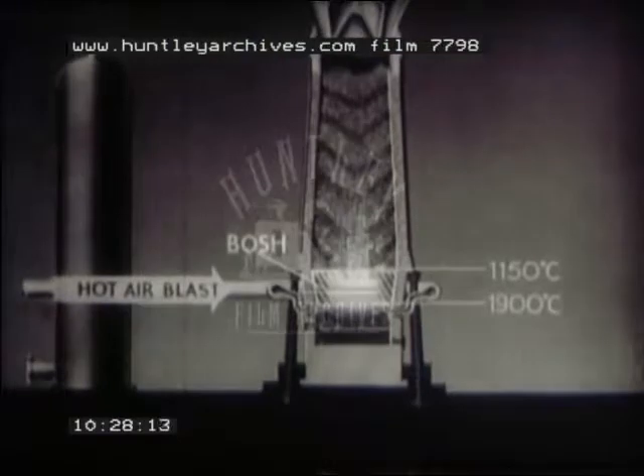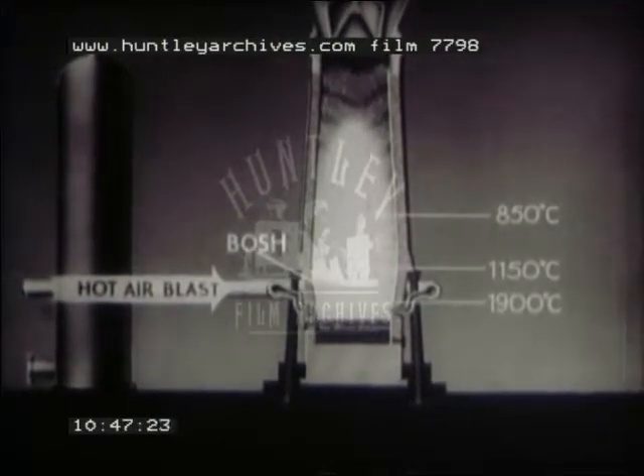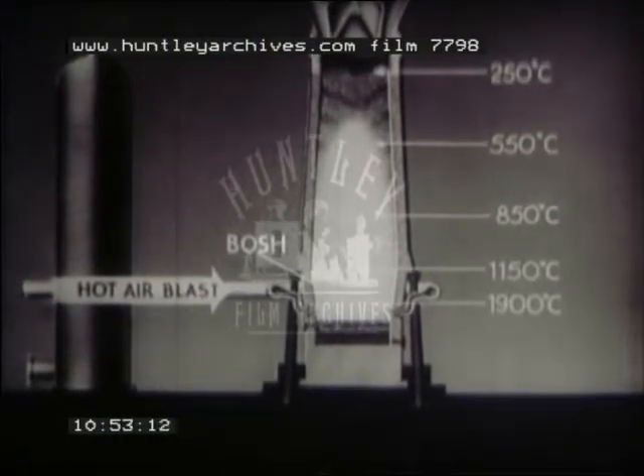We can now look at the process as a whole. The hot air blast enters the furnace at the bottom, where the coke burns and produces intense heat. The whole charge in the part called the bosh here is at a temperature of about 1150 degrees centigrade, rising to 1900 degrees opposite the tuyeres. As the white-hot gases stream up the stack, they heat the burden, and in so doing lose heat themselves, so that they're progressively less and less hot the nearer they are to the top. At the very top, where the gases leave the furnace and the cold raw materials go in, the temperature is only about 250 degrees, well below red heat.